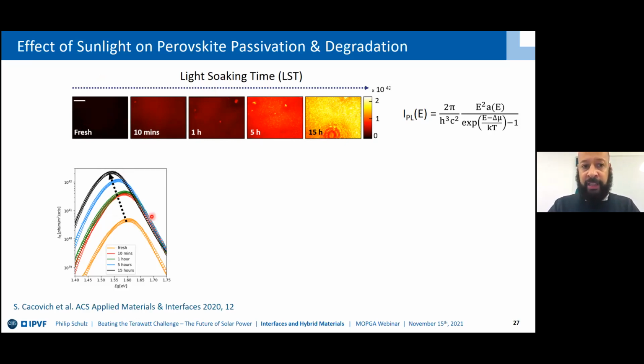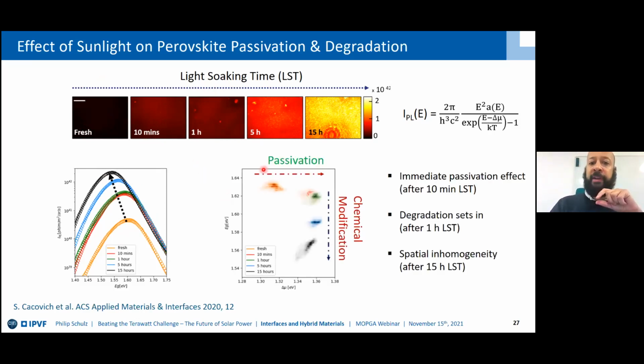We look at these spectra, so these are really spectrum images. So not just looking into physical features, but on how light is emitted from each pixel. And then we can draw maps of the different band gaps, so optoelectronic properties, versus the chemical potential. And we see that first we have an immediate passivation. So when you expose your perovskite film to air, it will reduce defects. But then after a while, degradation sets in, and there is a time window in which the material becomes worse and starts to degrade. And with the XPS, we're actually able to really detail these changes.